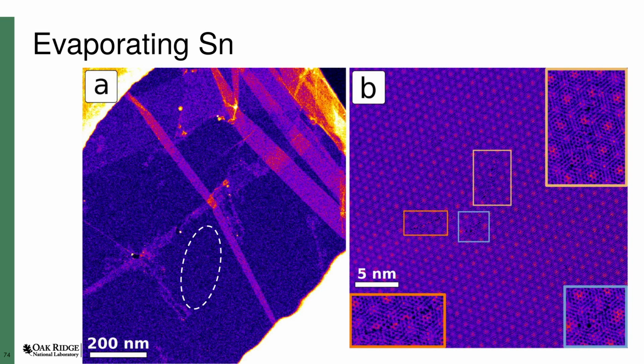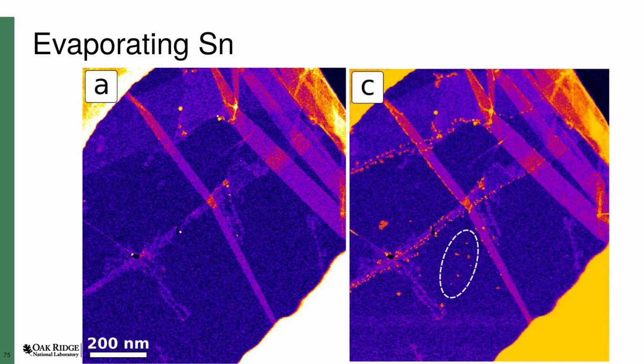Here we've heated it up to clean it, and in this dotted oval we took a few high-resolution images and introduced a few damage sites shown in the boxes. Then we heated the filament. These are the before and after images. The little bright spots are the tin that has been deposited onto the sample. Most of it has attached at step edges or wrinkles, but we do see some bright spots where we damaged